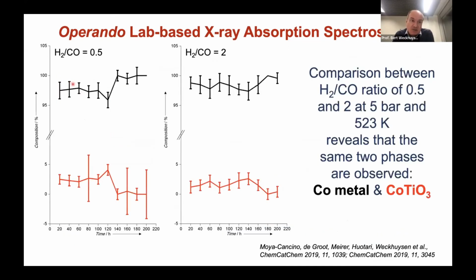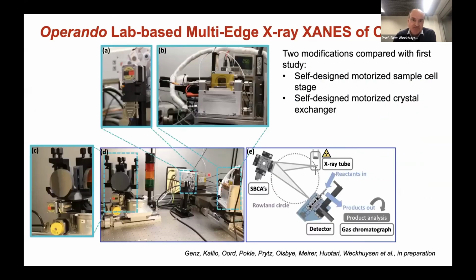And I already showed you before this kind of plot where we have been using cobalt metal and cobalt titanate to plot and see what is happening and what is present in the catalyst. Mainly metal, and although you see the error bars, some titania oxide, titanate phase. These are the papers which we published together. This may be interesting for the one who also asked questions about cobalt carbide, which we also studied in this follow-up paper, on cobalt carbide formation.